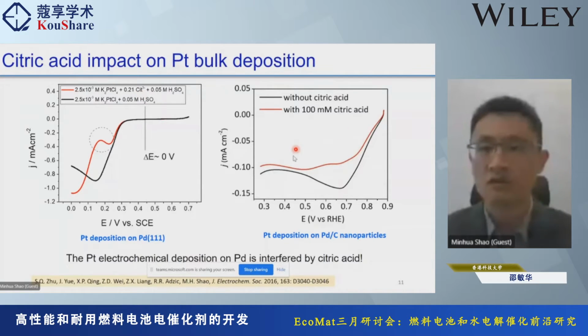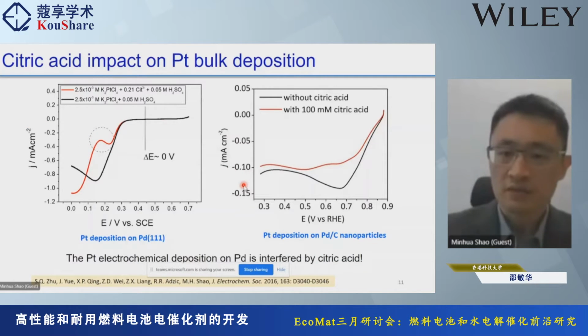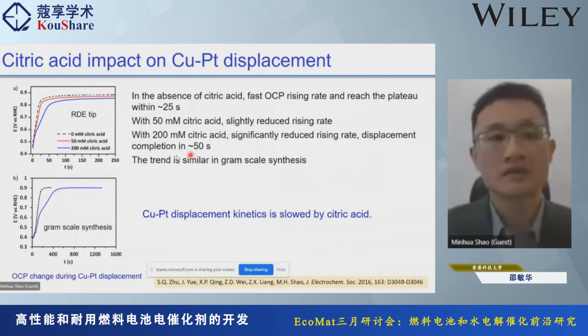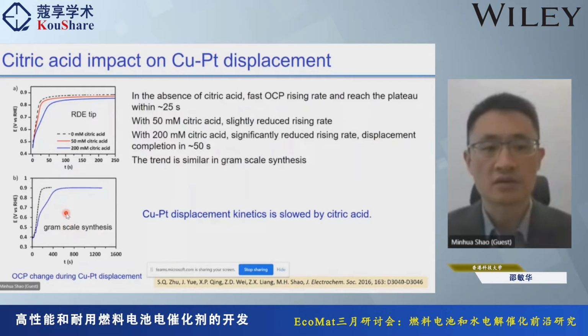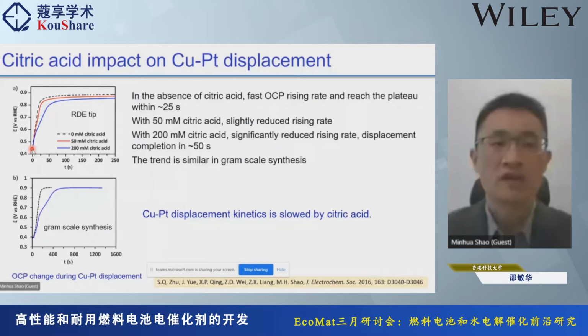And we did this on the nanoparticles, and a similar phenomenon was also observed, but of course this is not a single crystal, so you will not see this kind of inhibition as clearly as on the single crystal. So we found that the citric acid plays a role in the deposition kinetics. We did this on the RDE and also on the mass production batch. Here we measure the open circuit potential change of the electrode. Because the electrode is initially covered by a copper monolayer, the open circuit potential is low. After you replace it with platinum, the open circuit potential goes up to reach the platinum open circuit potential. So you can monitor this change. Without citric acid, the increase is very fast on the RDE, 25 seconds, and the whole process is done.